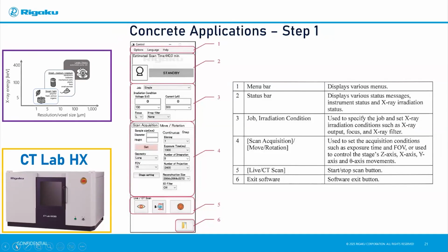This includes changing the voltage, current, and focal spot size of the X-ray source, mechanical filter, for example, aluminum or copper, moving the sample relative to the X-ray source and detector, correcting the field of view, detector properties, for example, pixel size in the form of binning, the number of two-dimensional transmission projections, the number of iterations, and many other settings. Concrete samples can vary widely, so CT settings may differ from one to another. For example, for a concrete sample, after several preliminary short test measurements, I found that a voltage of about 110-130 kV and a current of about 120-150 microamperes with an aluminum filter provide relatively good contrast, as shown in the previous slides.